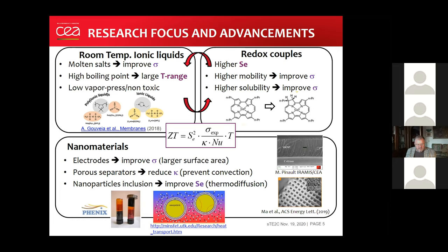And last but not least, which is the focus of our projects in Magenta, is the use of nanoparticles. The charged nanoparticles that are being introduced have a higher entropy, and therefore a higher chemical potential dependence on temperature. And this can be used to improve the Seebeck coefficient.